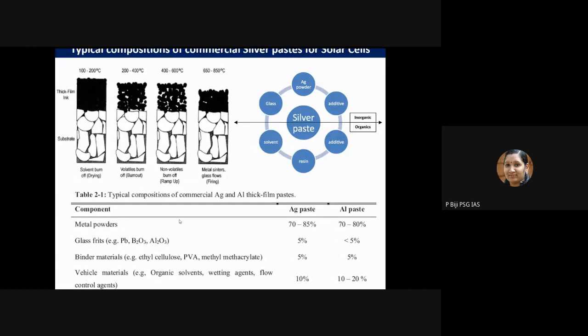After this drying process, in the next stage, if you increase the temperature up to 200 to 400 degrees Celsius, the volatile matter burns out. Then after that, they will increase it up to 600 degrees Celsius. At that time, the non-volatile matter will be burnt out.